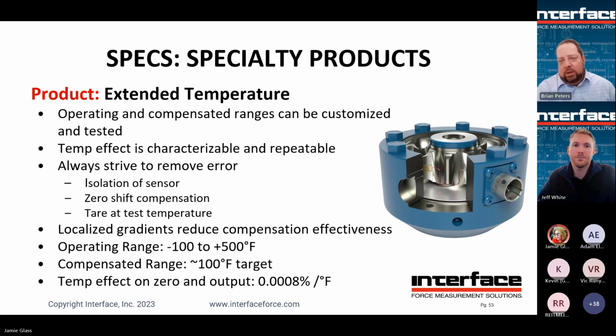So the compensation effectiveness may vary, especially if you have, let's say, a hot or cold airstream right on that little machine pocket. That's where we finish out some of our zero comp, and we do our temp comp. It's usually behind the label on an Interface load cell. You'll feel a little hard cover there. If you have a localized temperature delta at that pocket versus the rest of the sensor, temp comp may be delayed or it may not even be accurate. So that's just something to keep in mind.